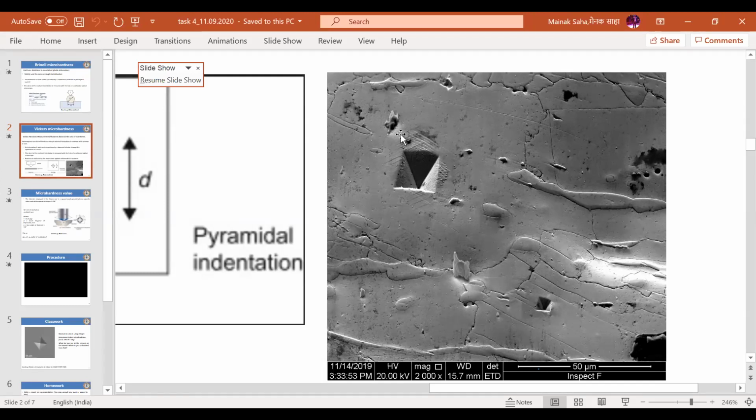What are you going to see? You are going to see slip lines around plastic deformation. If you are able to see these lines, they are actually a bunch of dislocations, a bunch of geometrically necessary dislocations. You can note this term down. Study this first, then later I can explain what GND is. These geometrically necessary dislocations have developed around the different indents.